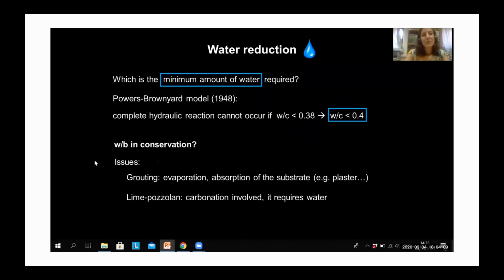separate, let's say. So we have this magic number, which is just in theory though. What about in conservation? What's the water to binder ratio in conservation? There are some issues, of course. For grouting, there is evaporation occurring, obviously. There is absorption by the substrate, for example, by the plaster. And we said indeed that in lime pozzolan, there is a hydraulic reaction occurring, but also carbonation is involved, which requires water. So this is just an indication, but of course, we need a bit more water than that, if we think about the minimum we need.